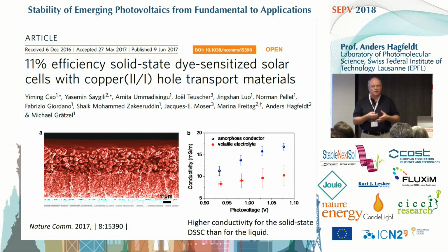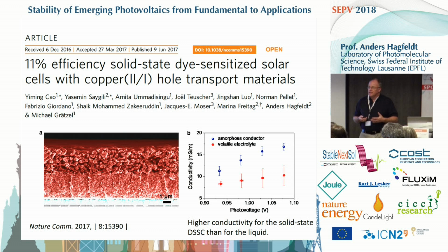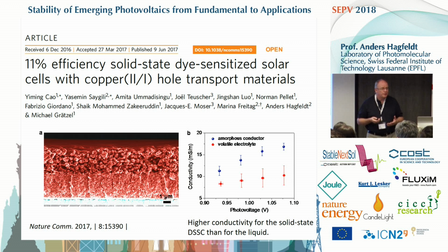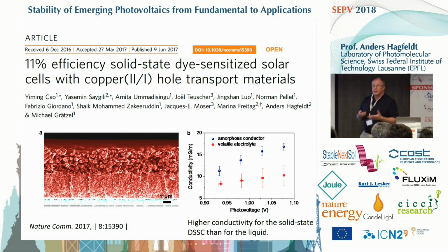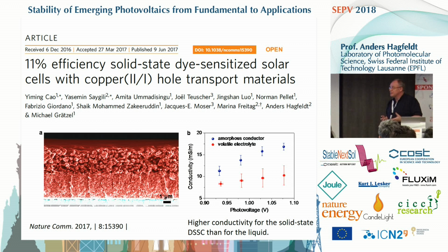After a month, we had cells on the shelf that had leaked out and dried out, which we normally threw away into the glass bin. Our technician at the time, for some reason, had perhaps nothing else to do, I guess. So he took these old dried out cells, measured them, and measured higher efficiency than in the liquid state. Very strange to us. We call them the zombie cells, actually, because they should be dead, but they are somehow alive, and we try to understand what's going on.